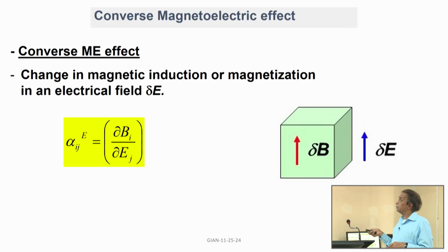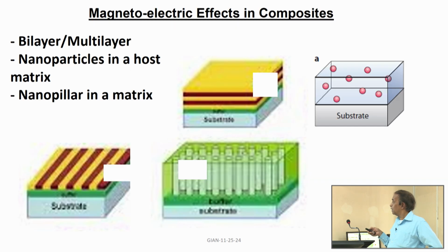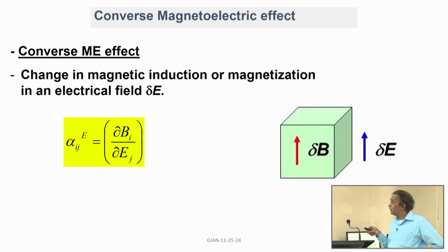And the converse effect is the change in the magnetic induction B, or the magnetization, with electric field, and you represent this with a superscript alpha E, that is dB/dE. And you can show that the alpha in the two cases are one and the same, they are not different.